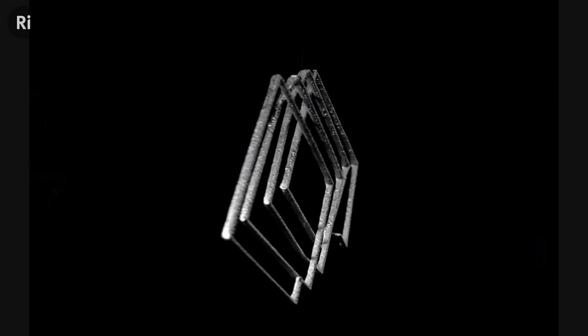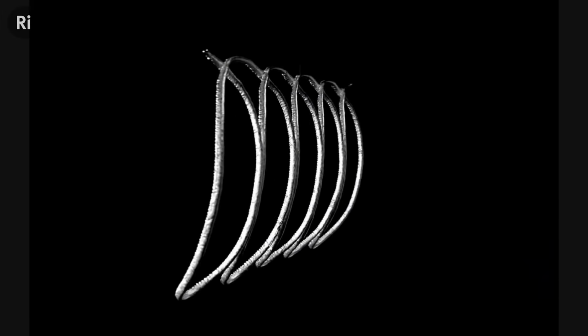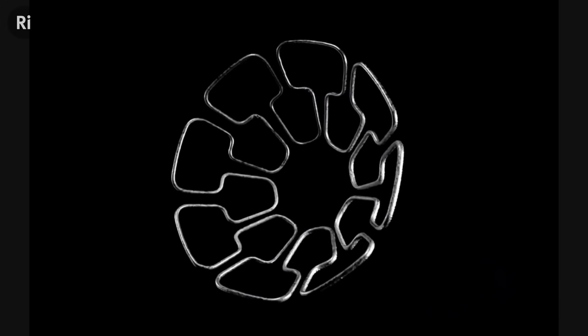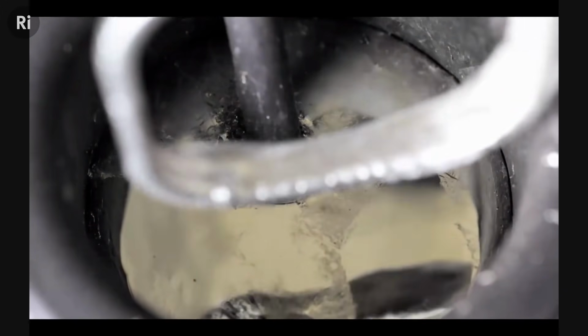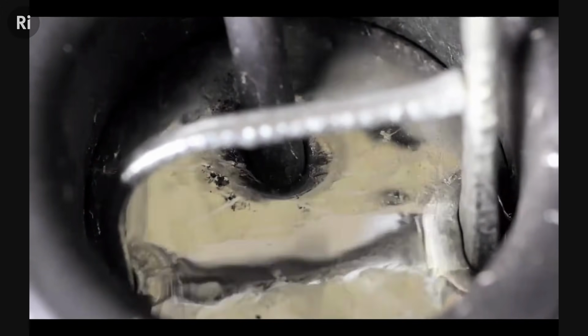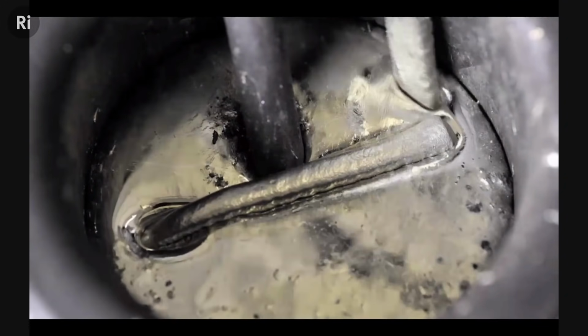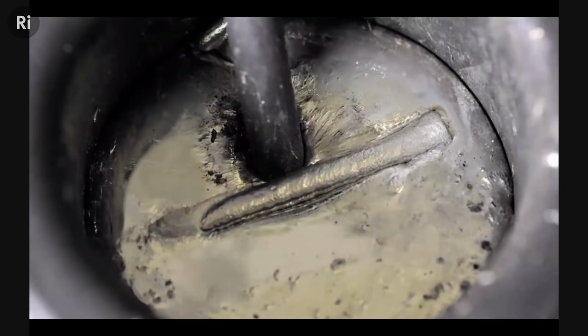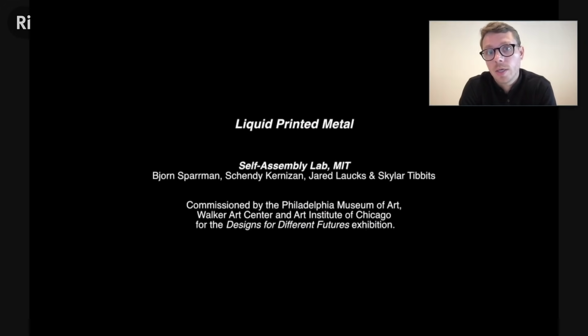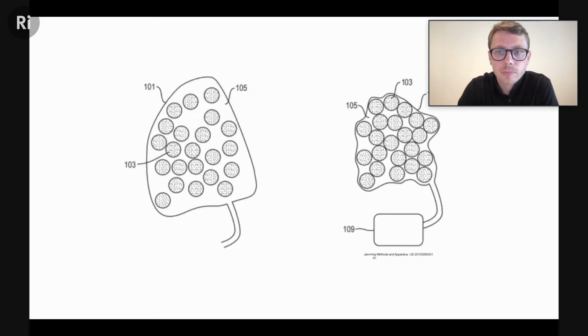So we print, because the metal cools in seconds, we can print large scale structures on the order of meters very, very fast, in seconds to low minutes. It's then almost instantly solid. So you can make these large scale metal structures like baskets and furniture pieces. And what's most interesting is that it's 100% recyclable. So everything you print can then be melted directly back, printed again, over and over and over again. So it's almost like Control Z. You can undo, print, reprint, and there's no waste in that process. So we're really interested in this solid to liquid, liquid to solid transformation.